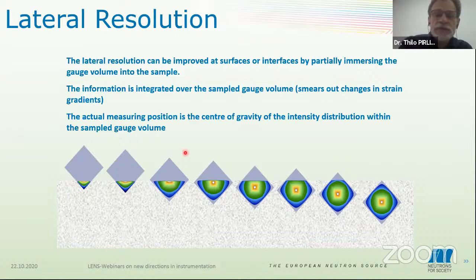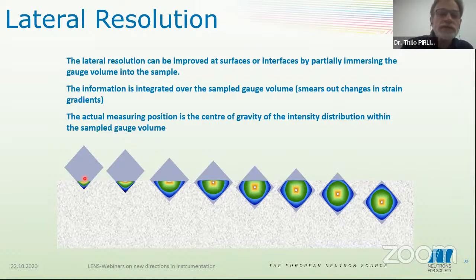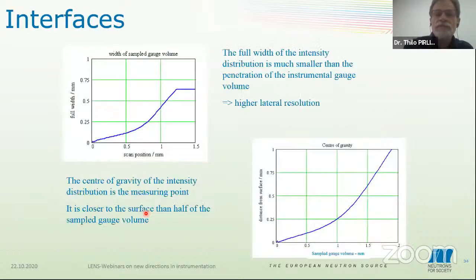The maximum we could reach was 40 micrometers from the interface. This works perfectly in combination with x-ray diffraction, where you are very sensitive to the surface. Combining these two methods, you get a complete stress profile of your sample.